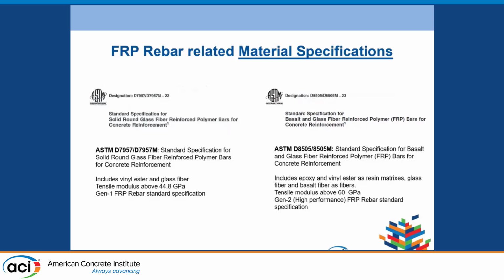ASTM D8505 was published last year, in April. It set a higher standard for FRP rebar, considered the generation 2 or high performance FRP rebar standard specification. The tensile modulus requirement is about 60 gigapascal, and other properties like the transverse shear and pullout bond strength are also higher. It includes both epoxy and vinyl ester as the resin matrix, and also glass fiber.